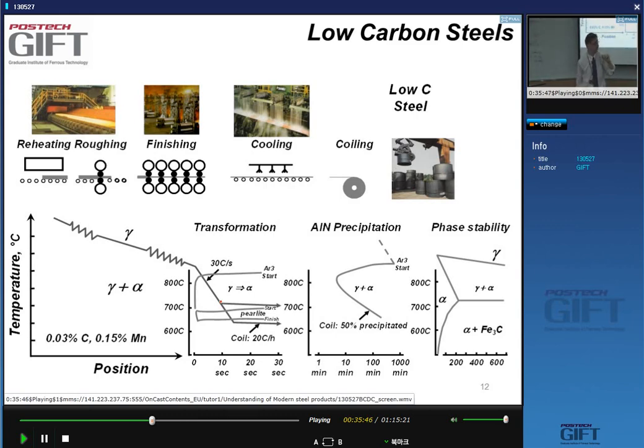So this is when you cool in the runout table, you have about 20 to 30 degrees per second, and then when you cool in the coil, your cooling rate is like 20 degrees per hour, or much smaller. So that's why you have a change in slope here. Okay. So when I do a high temperature, I actually don't form pearlite. For those who don't see what I mean, if you do a high coiling temperature like here, it means that you coil at this temperature and you go very, very slowly through this region below the A1 line, and so you basically make cementite very slowly, and you get blocky cementite.